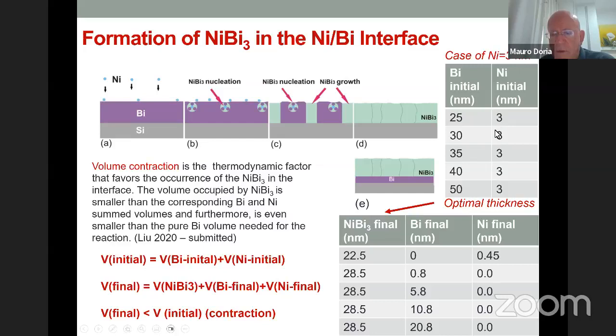All right. So we looked at two systems. For instance, one is an initial layer of nickel deposited on bismuth. The nickel basically disappears and forms nickel bismuth 3, and you are left with a layer of bismuth. In the case that there is not enough bismuth, I think it's this 25, you eat out the bismuth, but there is some nickel left over, so you can have that. But if you have enough bismuth, all the nickel reacts and forms nickel bismuth 3, okay.